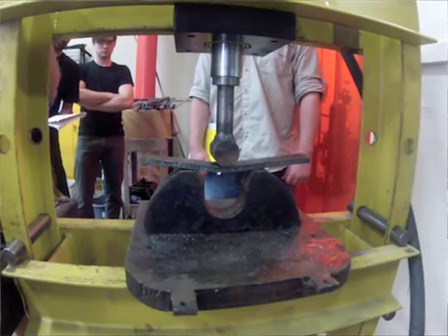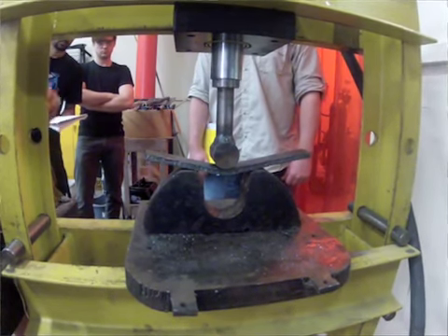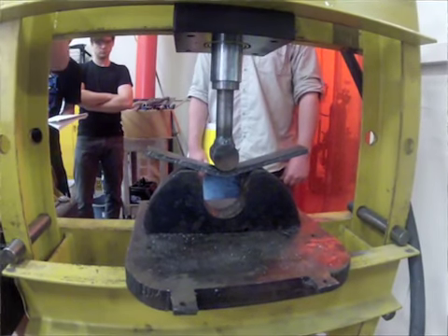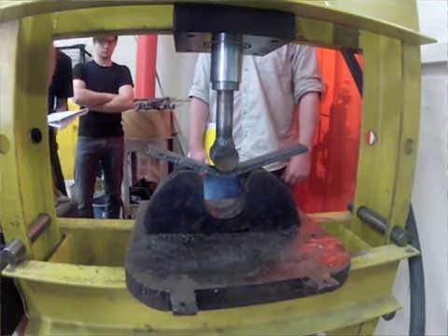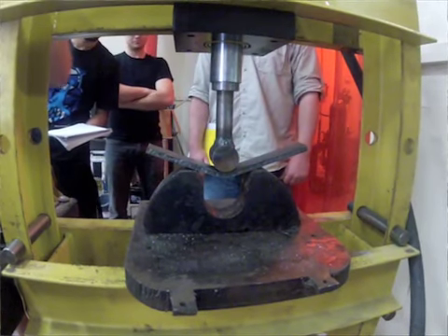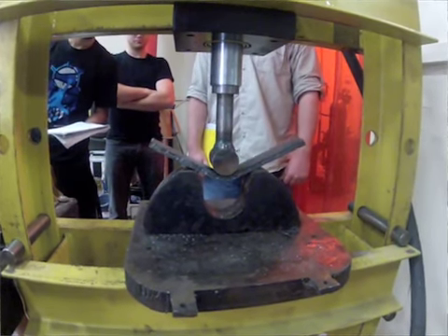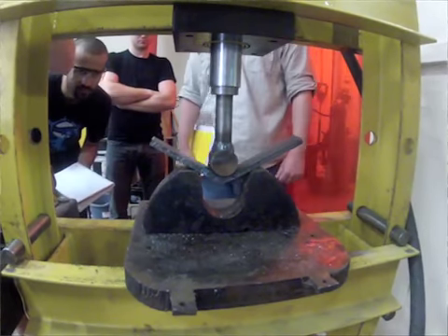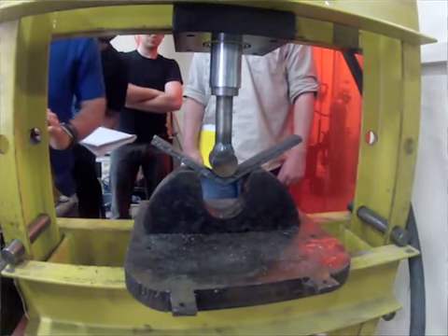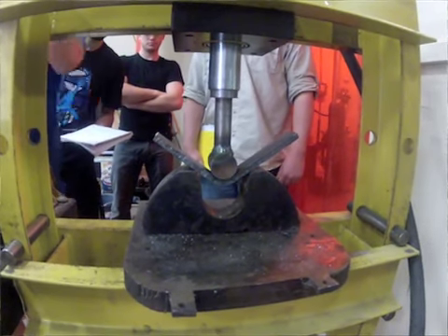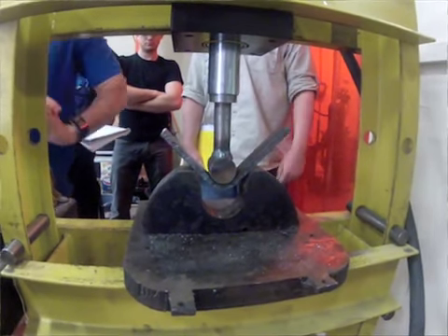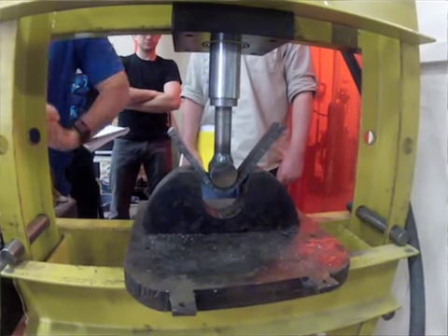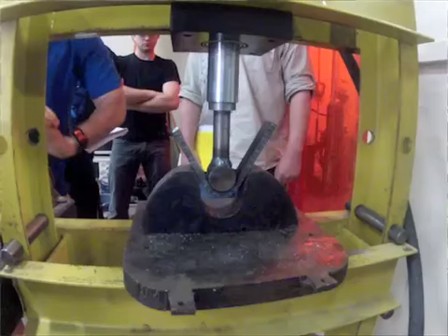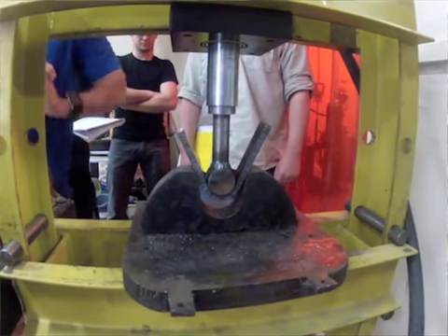During this experiment, the metal bar was placed in the bending machine. The bending machine applied force to the center of the bar to measure the amount of psi it would take to break the bar. As pressure was applied to the center, the bar just kept bending but did not break. After reaching a maximum of 18,000 psi, the bar was removed.